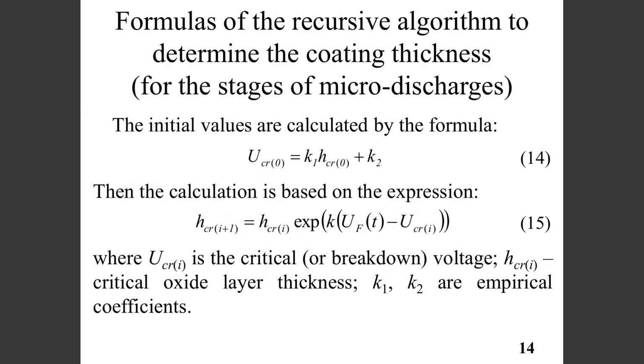The breakdown voltage UCR of i equals UCR of 0 determined at point B of the forming curve, and the initial value of critical thickness HCR of i equals HCR of 0 found from the expression 13 serve as initial data for the calculation. These values are substituted into expression 15, according to which the thickness of a micro-arc oxidation coating is calculated until the next break of the forming curve, point B1. From now on, the value HCR of i plus 1, which is taken from the previous iteration for point B1, and the voltage UCR of i plus 1, found at the point from the forming curve, are substituted into expression 15. Thus, the value of the micro-arc oxidation coating thickness at the stage of microdischarges up to the arc is determined.